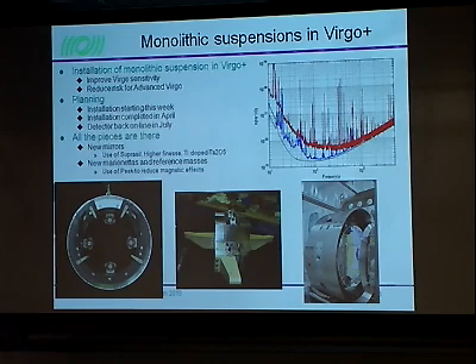We are profiting from this stop to change the mirrors with new Suprasil mirrors and to increase the finesse of the cavity. We will also use the most recent coating. We are profiting from this stop also to change some of the features of the payload. The marionettes and the reference mass which are used to control the mirrors have been changed in order to reduce the amount of metal near the mirror. We have seen problems with eddy currents. We have seen problems with magnetic sensitivity to external magnetic fields. So now all these parts have been replaced with parts made of PEEK in order to reduce these magnetic effects.